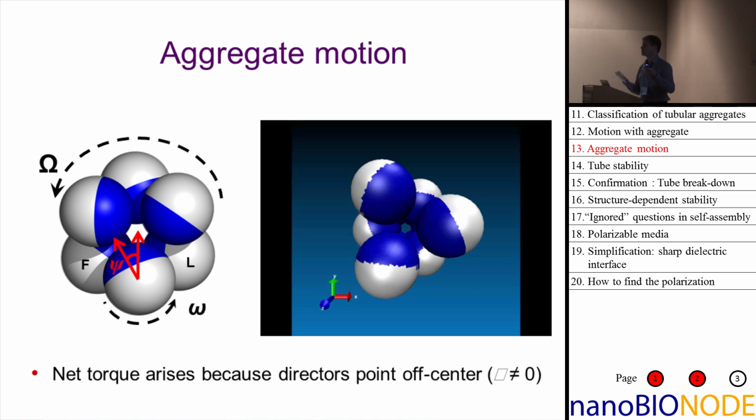So as soon as that would happen, the whole thing would fall apart. So the only answer, the only compromise that's possible is if the tube itself rotates as well at exactly the same angular frequency as the individual particles. So this lowercase omega must be the same as this uppercase omega. So the whole tube must rotate such that the blue side remains facing inward.